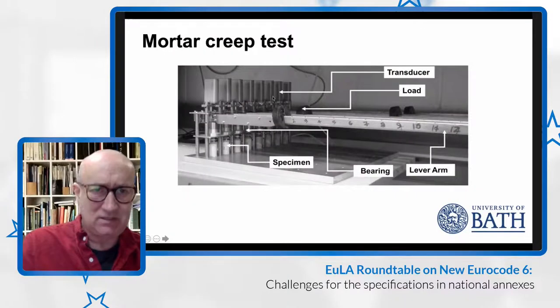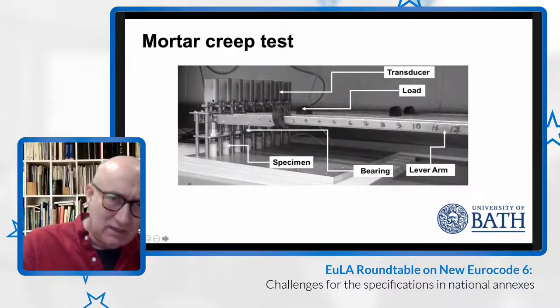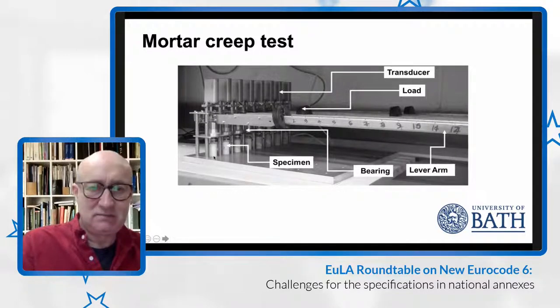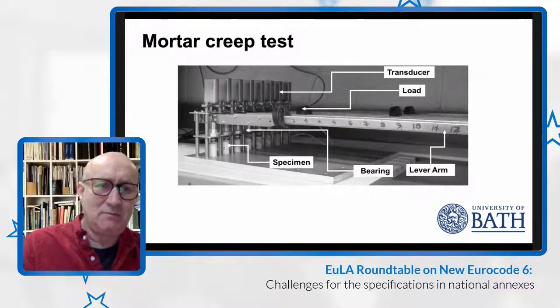So, specific to the tests here, this device, which was developed by my colleague Richard Bull when he was at Bristol University, uses LVDTs, and they are measuring the reduction in height of these mortar specimens. They have quite low travel, but they are very precise LVDTs. So we are measuring the change in height of the specimens.